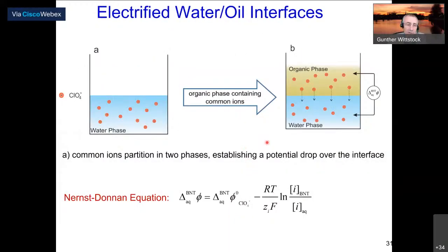I would like to explain this stepwise a little bit more in detail with a few examples. How do we get the nanoparticles to the interface? This sounds difficult at the beginning, but turns out to be very easy. We start with an aqueous phase, which contains a salt like perchlorate. Then we add the organic phase. In this case, the organic phase is lighter, and it also contains a perchlorate salt. So now we have perchlorate as a common ion, and that will partition between the two solutions. Usually some of the perchlorate goes from the organic phase spontaneously to the aqueous phase. They take their charge with them and charge up the aqueous phase negatively, and the organic phase will be positive. That generates the potential difference between the two phases, which can be calculated by the Nernst-Donnan equation. The ratio between these ions in the two phases is important. By manipulating the ion composition, we can vary the voltage, similar to applying a voltage over a potentiostat.